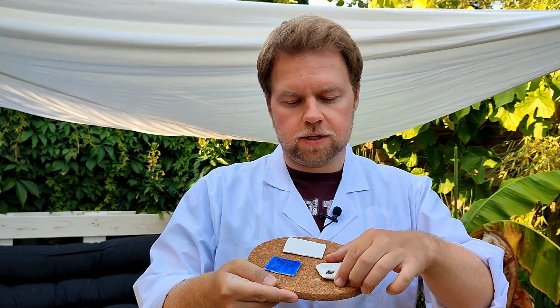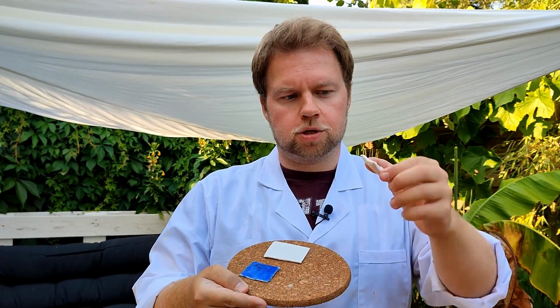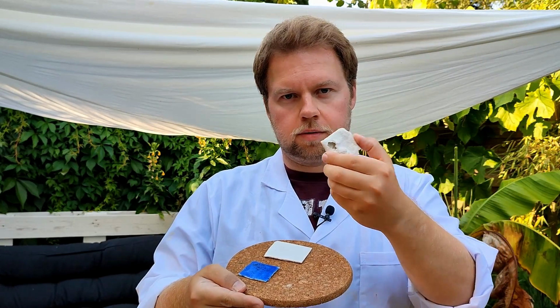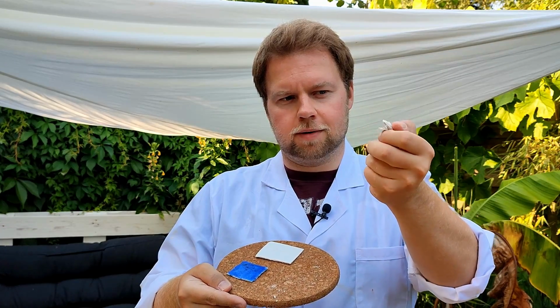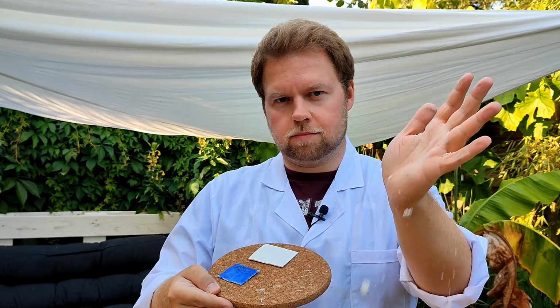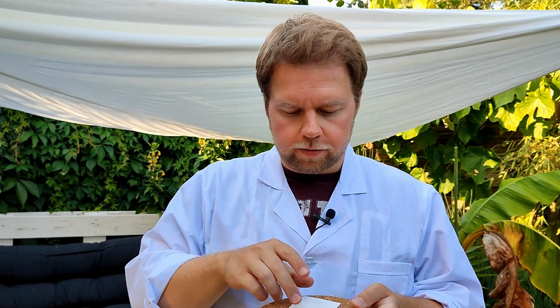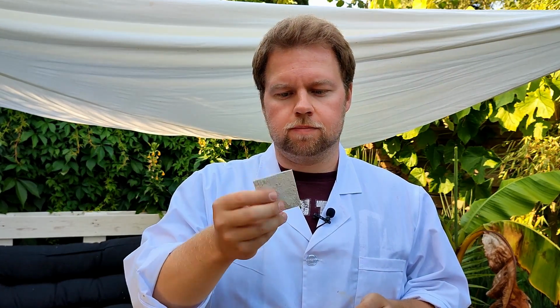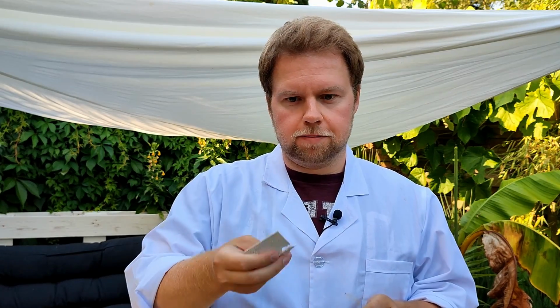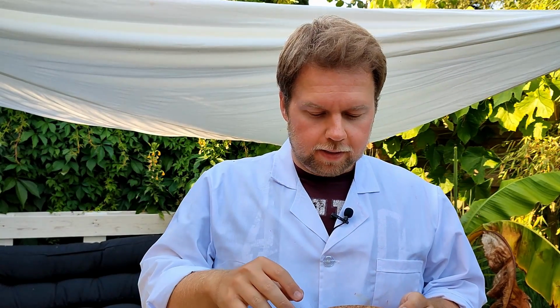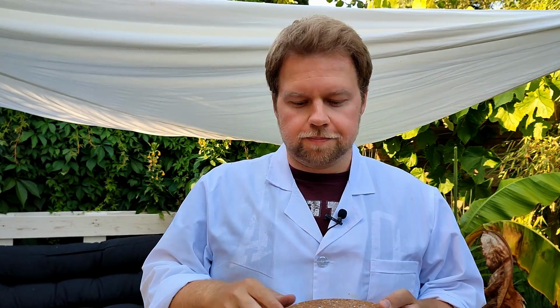So as you can already see, the 33% mixture did come out, but it just crumbles to dust completely. That's pretty bad. So quite crap. Now, as for the 50-50 mixture, it feels a bit better, but it's basically the same. Just crap. So I call that a total failure.